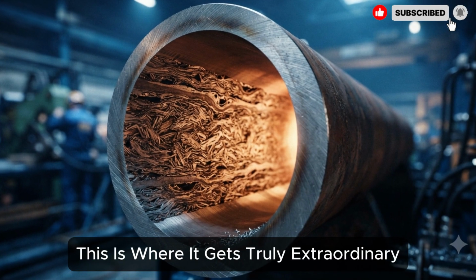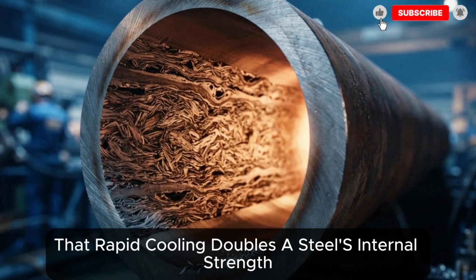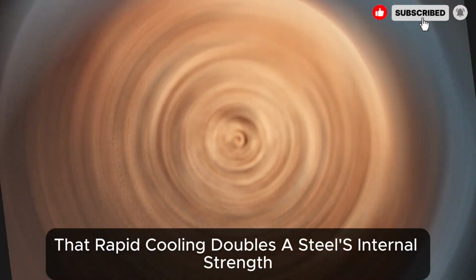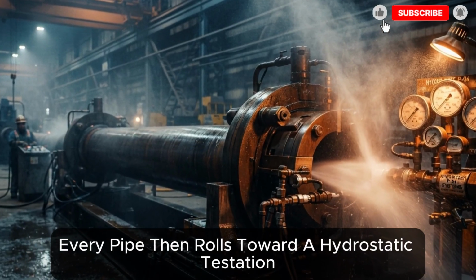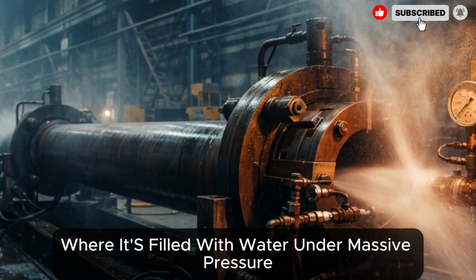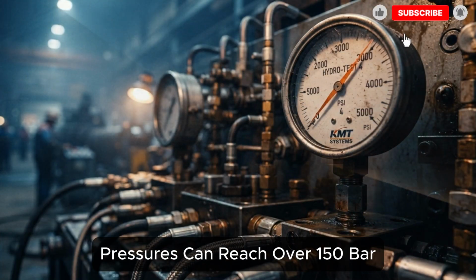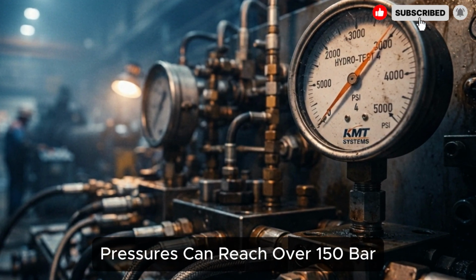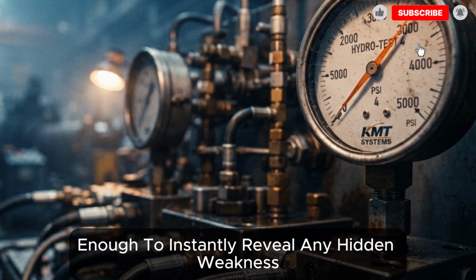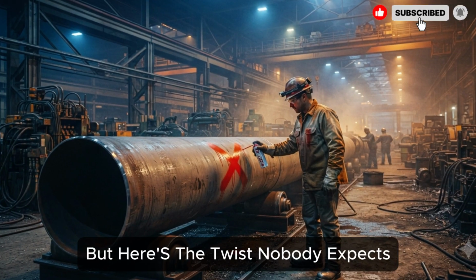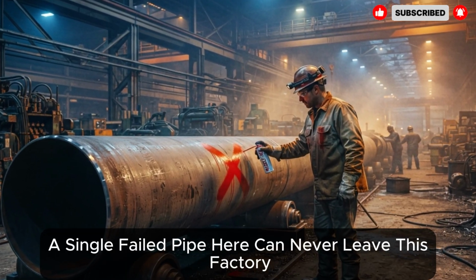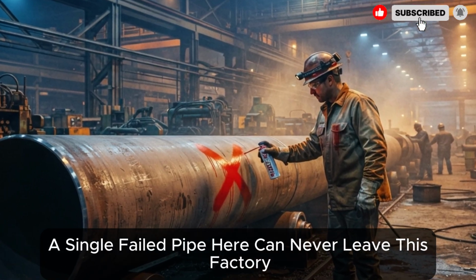This is where it gets truly extraordinary. That rapid cooling doubles the steel's internal strength. Every pipe then rolls toward a hydrostatic test station, where it's filled with water under massive pressure. Pressures can reach over 150 bar, enough to instantly reveal any hidden weakness. But here's the twist nobody expects. A single failed pipe here can never leave this factory.